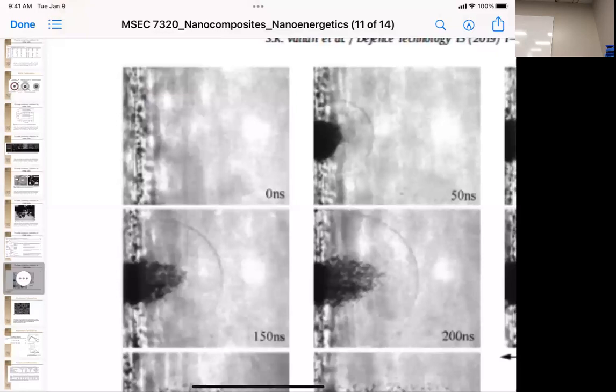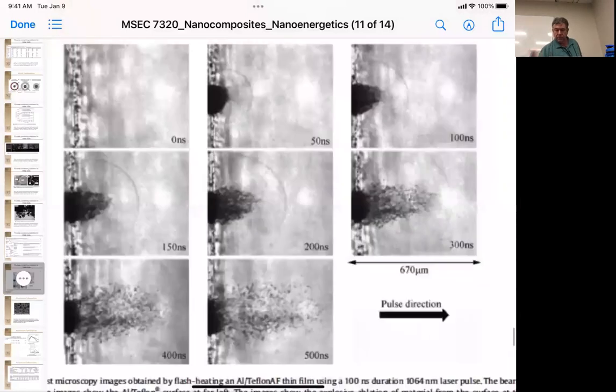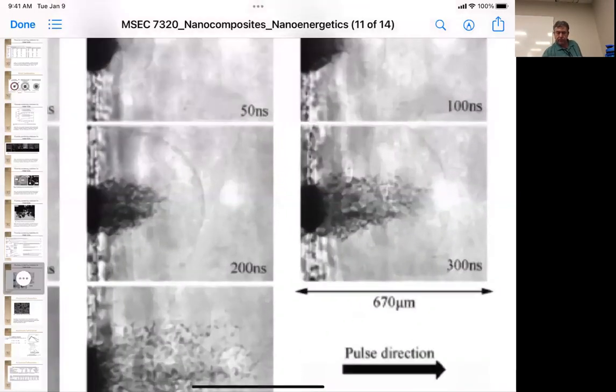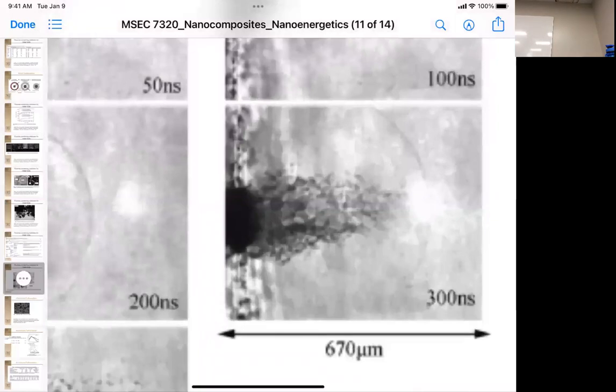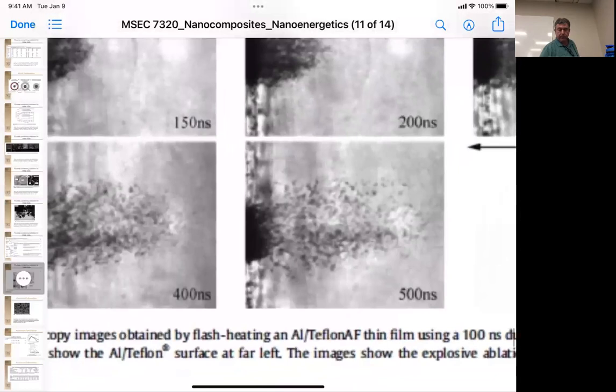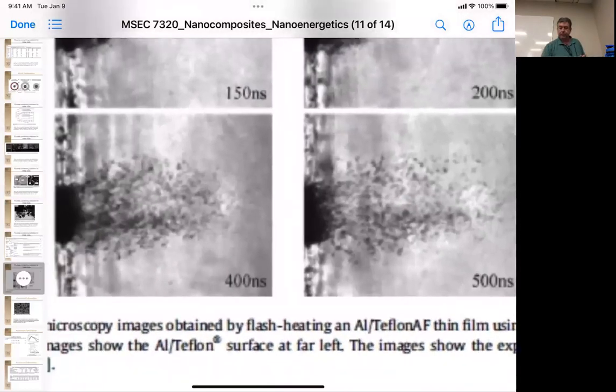So this right here, there's a, not Riley lines, there's a name for these lines. This is your pressure wave extending out after 150 nanoseconds. And notice we're seeing the evolution of our aluminum fluoride materials coming out here. And then our pressure wave is increasing again with more generation of our solids coming off of our system until we get out to 300 nanoseconds. Our pressure wave is almost being hit by our solids here. And then we have a degradation of the pressure wave and we just have our solids come off right here.